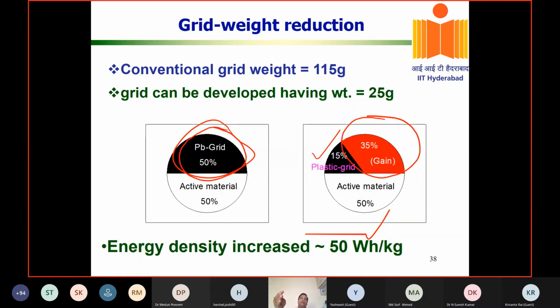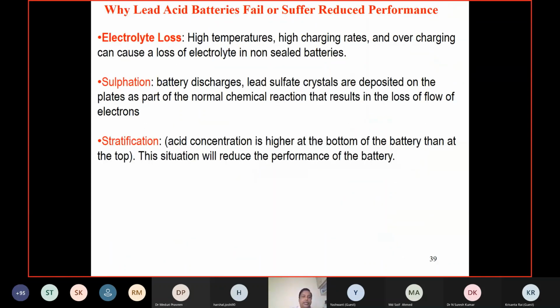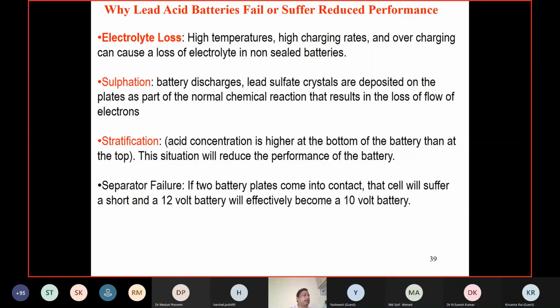So low utilization of active material, water loss, grid corrosion, weight reduction, and then there are many other issues like the sulfation at the negative plate. In a lead battery, sulfation is always formed at the negative plate. Negative plate sulfation is one of the major issues in lead-acid batteries. Once lead sulfate is formed at the negative plate, it doesn't allow the electrons to flow and ions to move, and the battery stops immediately. And already I told you about electrolyte loss. If it is at high temperature, there is a possibility of loss of electrolyte, more so in a non-sealed battery like flooded batteries. Stratification, that means if it is a tall battery, the concentration at the top and bottom will be different. The stratification will also make a problem.